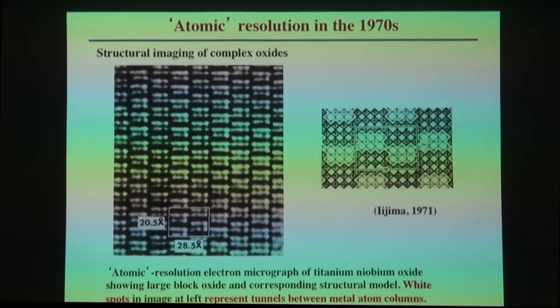So let us move on and start talking about getting atomic resolution. And the first atomic resolution was actually not resolving atoms. It was imaging by Iijima in Arizona in 1971, and he was looking at these block oxides, and these block oxides are lots of octahedra that share corners and share edges. And here is the image that Iijima took back then, and it turns out that these white spots are where the columns of atoms are not located. This is between the octahedra, so it's actually corresponding to the tunnels. And so in this case, the white spots represent the tunnels between the metal atom columns. So it wasn't really atomic resolution as such.